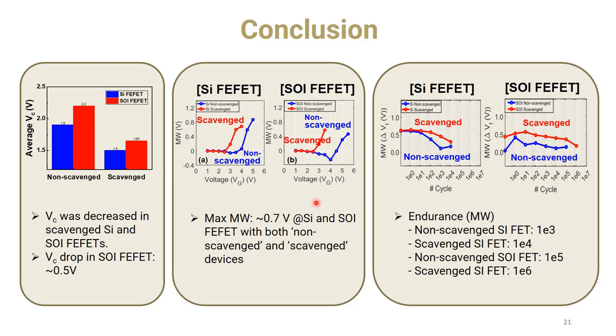In this study, we made 4 different devices: the non-scavenging device and the scavenging device for both silicon and SOI FET. And we measured the threshold voltage. There is a drop from the non-scavenging device to the scavenging device of around 0.5 volt. But that trend is pretty consistent in the silicon FET and SOI FEFET.